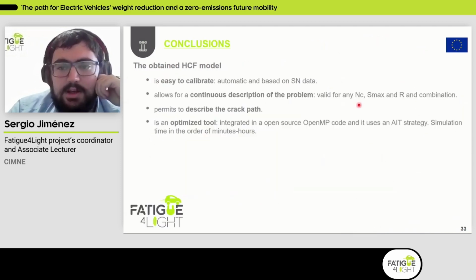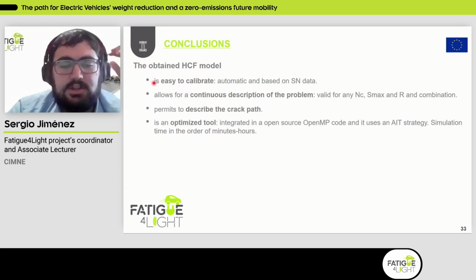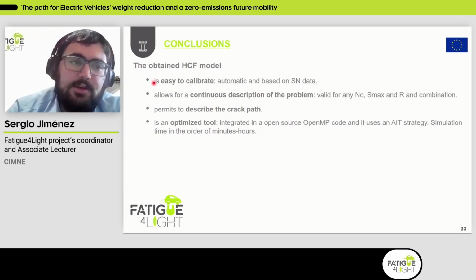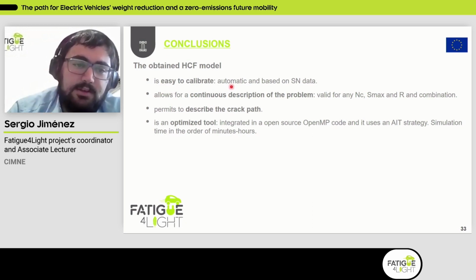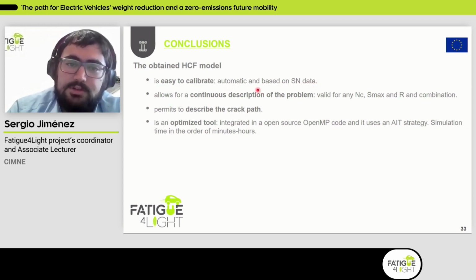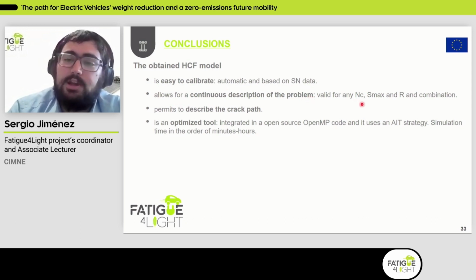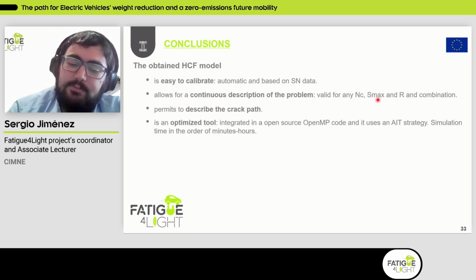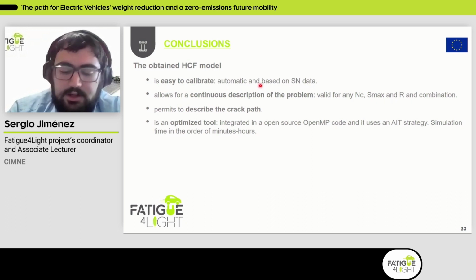And just to finish, I've drawn some conclusions here to summarize the key points about the numerical model that we finally created and applied along the Fatigue for Life project. As you may notice, this is an easy to calibrate model. Most of the process is done in an automatic way, at least for the fatigue part. And good news, it is based on SN data, so more or less everyone should know how to calibrate it. It allows a continuous description of the problem. So once you've calibrated, you can change the load that you used to build the SN charts, and you can still use the model.